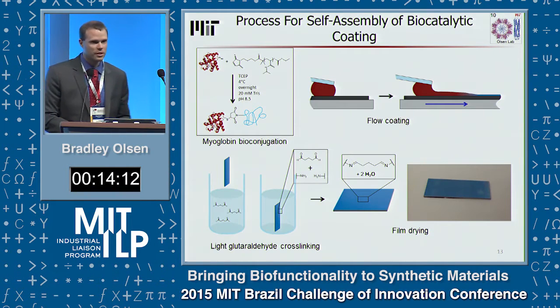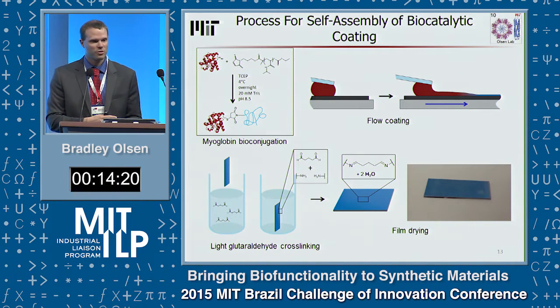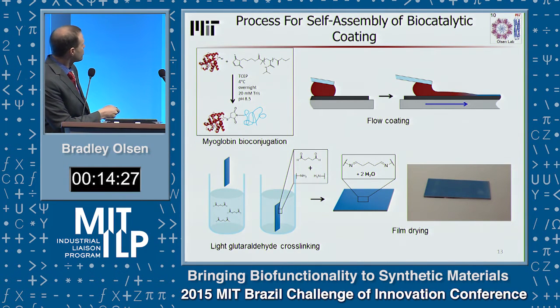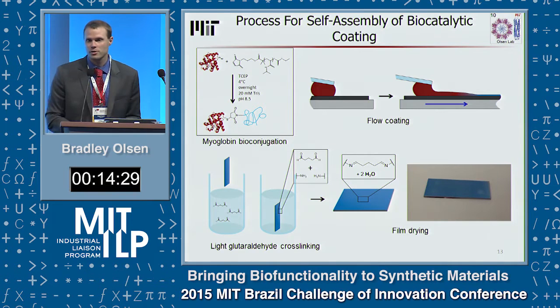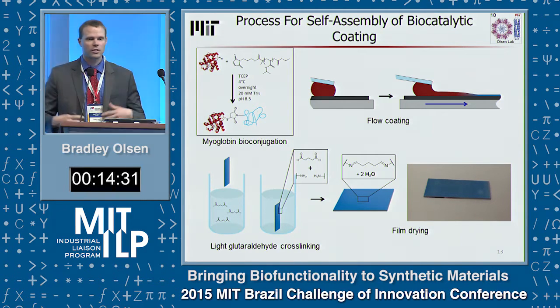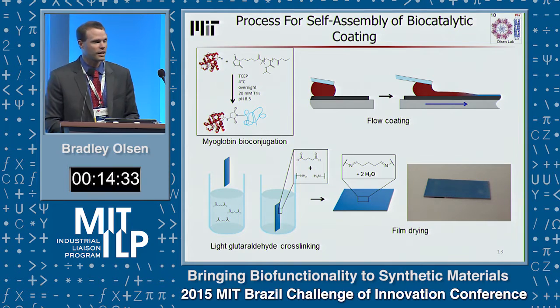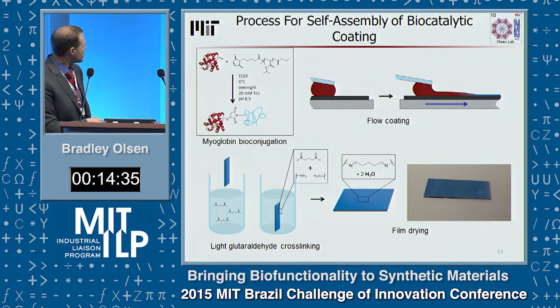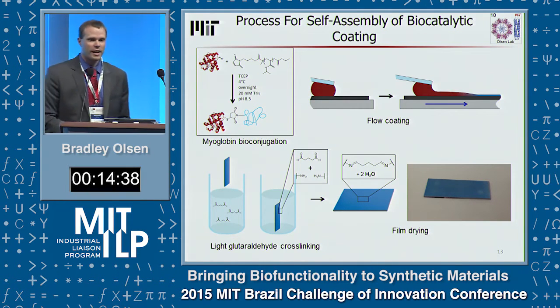What we then showed was the ability to integrate these sort of proteins into industrial processing. And so we developed a simple blade coating process for producing films of these materials in the range of hundreds of nanometers or microns thick. Basically you just use a fluid and coat it by a blade coating process. So this is easily scalable up to large-scale roll-to-roll manufacturing technology. You simply immobilize this by submersion in a bath with a cross-linking agent, and this produces a permanently immobilized protein film on the surface.